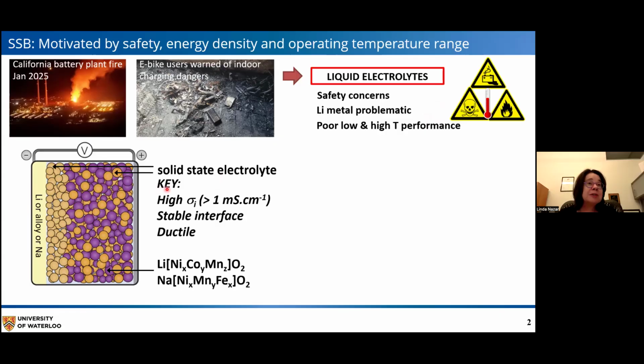And so in the solid state electrolyte, which is really the key in the battery, we have to achieve fairly high conductivity for the solid electrolyte, at least more than 1 millisiemens per centimeter. And we have to devise materials that have stable interfaces and are ideally ductile, because getting those interfaces with the cathode materials, which can be a variety of either lithium, sodium, or other materials, is of course critical.